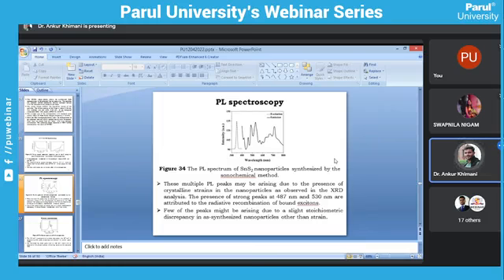PL spectroscopy, photoluminescence spectroscopy, in which we get the intensity versus wavelength graph. This is the excitation wavelength and this is the emission wavelength. Over here, these two graphs are merged. The PL spectrum of the SnS2 nanoparticle synthesized by the sonochemical method is shown. The multiple PL peaks arise due to the presence of crystallinity strain in the nanoparticle, as observed in XRD analysis.